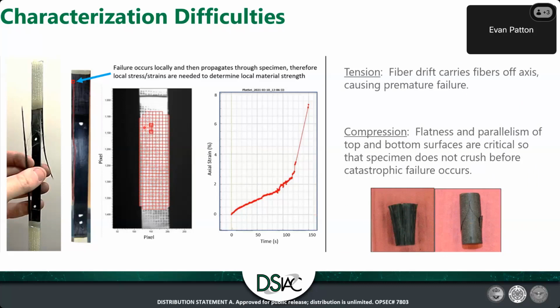And then moving over towards the tensile specimens, the left shows that piano stringing type of failure. Here, the fibers are actually off axis. So as that specimen was pulled, these fibers wanted to straighten out and follow their load path, causing these frayed edges here because the fiber axis was just ever so slightly off kilter. So to combat that, we did that DIC methodology, as I mentioned earlier, where we essentially looked at the DIC footage and tried to find a really nice representative area where we did have a crack appear across the specimen, even if it wasn't completely across the entire one. As long as it was across a localized area, we were happy with it.